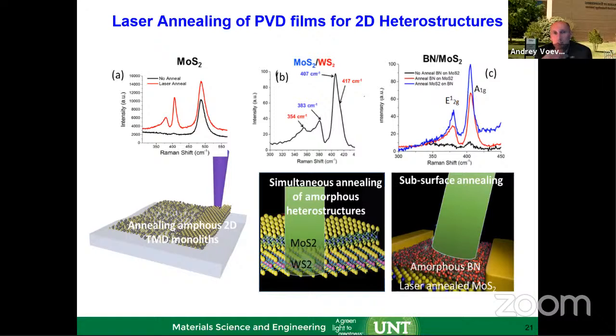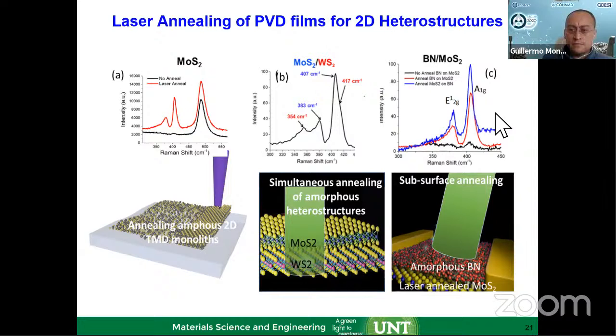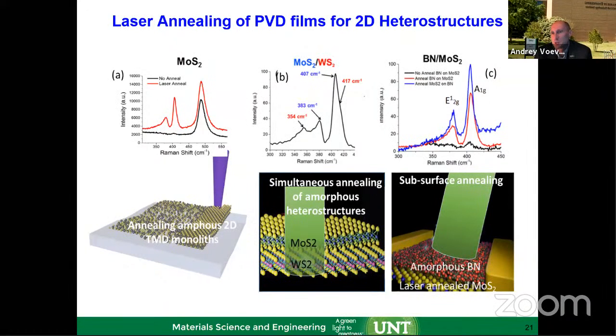Well, we're using 248 nanometer lasers. We also used flash lamps, arc flash lamps of different techniques, different wavelengths. And we found out, interestingly, not a high dependence on the wavelength, but a high dependence on the dose, on the joules per centimeter squared. We are a little bit perplexed by that because we thought the absorption would really depend on the wavelength. One thing we're thinking is that the PDMS is highly absorbing, so we are absorbing directly into the PDMS, and MoS2 is right on top of it and gets annealed. It is still a hypothesis, which our students are working on, and hopefully we can have the scientific answers.